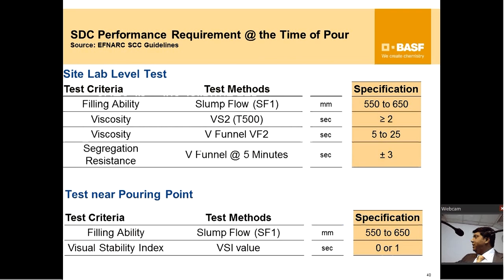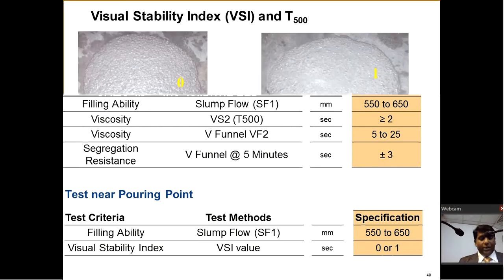Visual stability index between 0 or 1. So what is visual stability index? It is this. You check for the spread of the concrete. You do the flow table and you check the spread. This is as per ASTM C 1611.